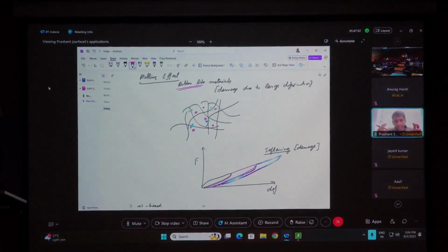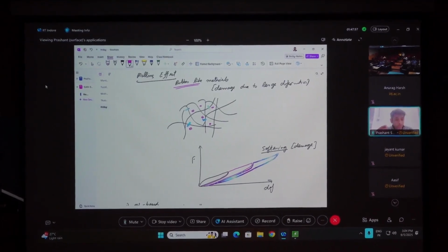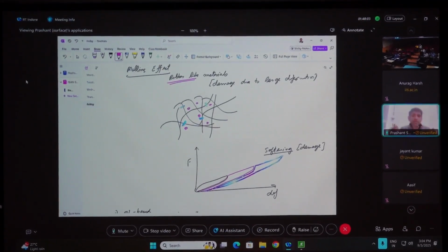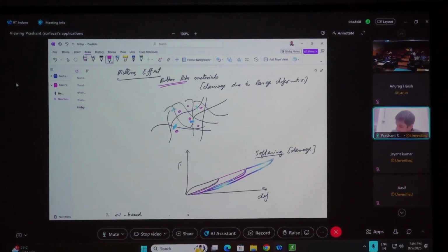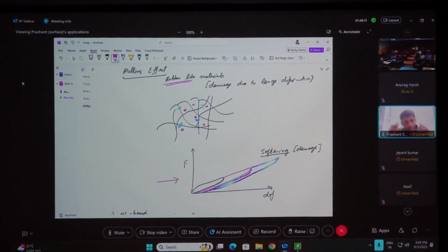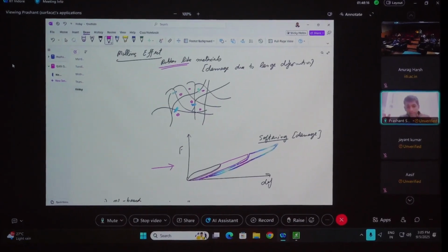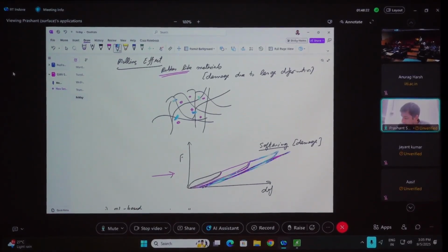And when it is created, at that time it is in a state where it is prone to a lot of damage. So that product, depending on what the material is, usually undergoes a lot of cyclic loading. So what you saw in this graph, basically, if you do enough cycles of loading in the new product, then you come back to this damaged state, which would be basically the final state of the material, and then it is launched into the real assembly line.